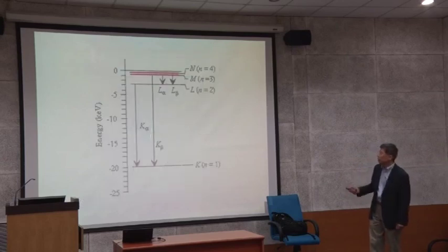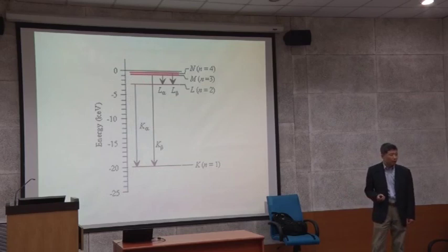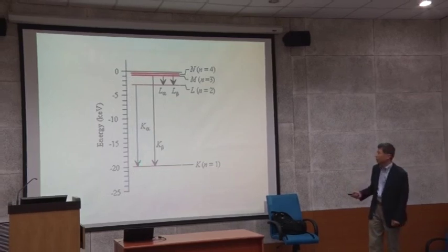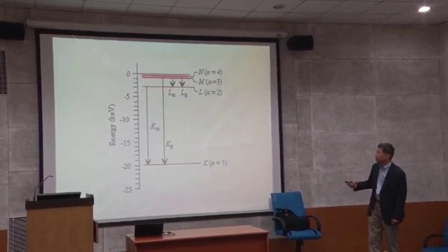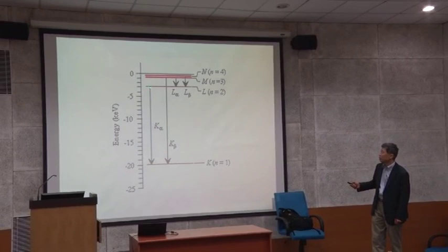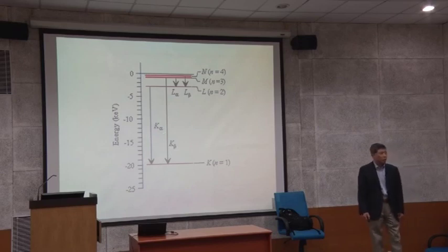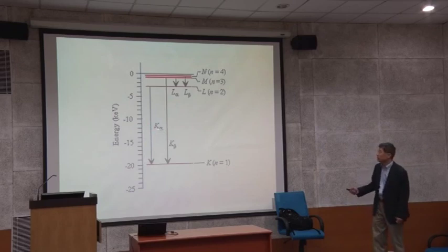So you can see that X-ray is coming from an energy transition, and what we call the K alpha line is coming from excitation of electrons in the K shell. The electrons are ejected, and electrons come from another shell. The K alpha line comes from the right next shell, and the K beta line comes from the second next transition, and that's why it has a longer wavelength than the K beta line, but this is the strongest line, the transition in copper.